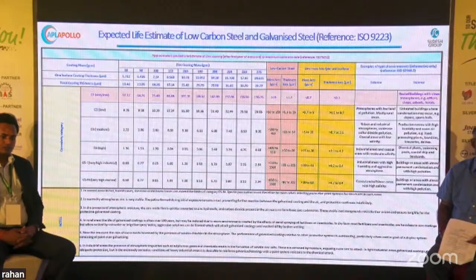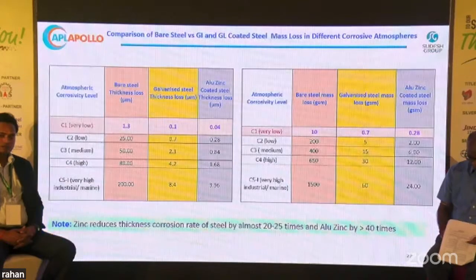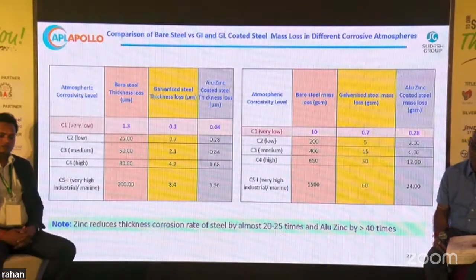In the second column, you can see there are 5 types of corrosive atmosphere, C1 to C5, where C5 is the most corrosive. This is the comparison table of the base metal, which is steel, and the yellow galvanized. It gives 20 to 25 times more life than normal steels, thus enhancing its life. As I explained in my earlier slides, alu zinc has 2 to 4 times more corrosion resistance than normal galvanized, so there is further life enhancement.